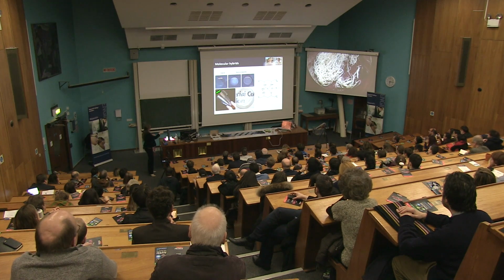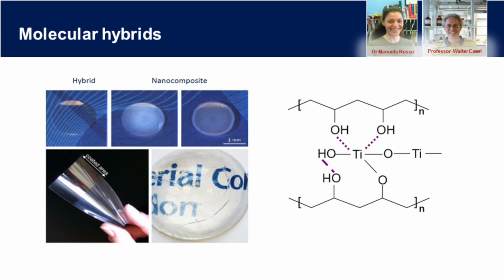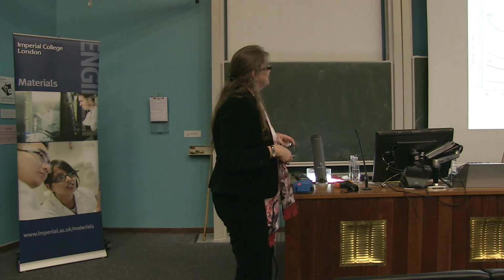And now you see we coated this so we can use very, very standard coating technique. So this is a piece of plastic. We coated here this high refractive index hybrid. And you see already, despite this is a plastic at the end, it looks already like very, very metallic. It reflects much more. It reflects more because we increase the refractive index.